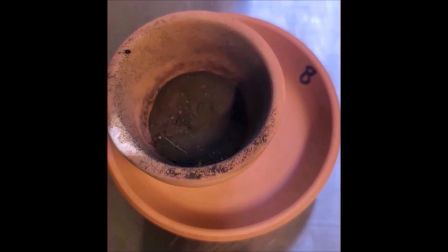Sample 8 afterburn displays as a solid mass with a powdered texture surface. A reason sample 8 was not molten was because the mixture had gotten moist, and this moisture presented itself at 2 times. The first time was pre-ignition, when it took significantly less volume of Fe2O3 to reach the required weight ratio. The second time was after ignition, where significant volumes of powder ignited well outside the diameter of the mini terracotta pot.